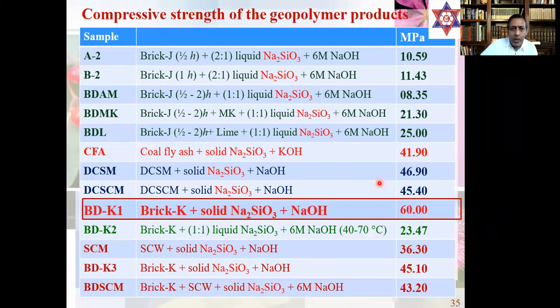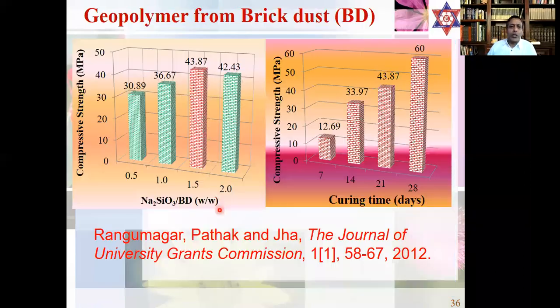So I varied a lot of raw materials, that is, inorganic waste materials, changing the chemical parameters, and the strength I got was a maximum of 60 megapascal. Geopolymeric material was obtained from the brick dust. So you will see here some variation with the sodium silicate and brick dust variations. These are some chemical parameter variations, and how we came to the conclusion with the highest compressive strength.